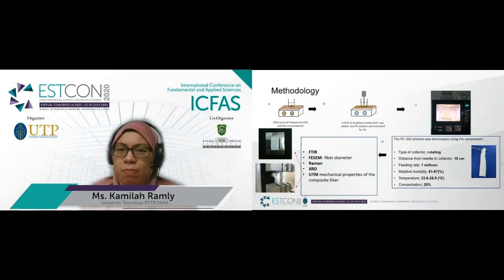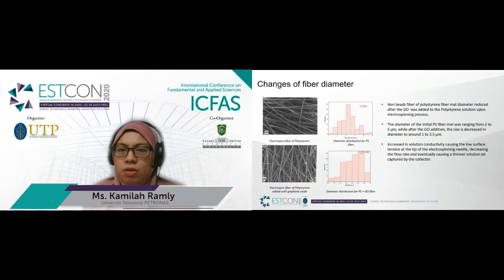Afterwards, this sample was subjected to FTIR, FESEM, Raman, XRD, and universal tensile machine to evaluate the effect of the addition of graphene oxide to the polystyrene solution. The change in diameter of the electrospun fiber was evaluated by FESEM. It was observed that the beadless polystyrene fiber mat diameter reduced after the graphene oxide was embedded into the fiber upon the electrospinning process.